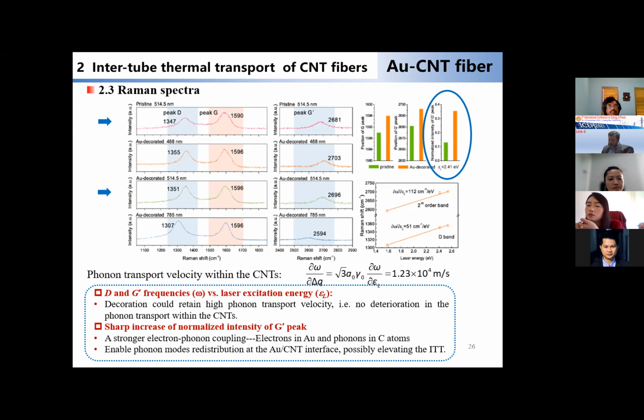Further examination of the frequency against laser excitation energy indicates that gold decoration could retain high phonon transport velocity, the same as the group velocity of the pure tube. That is, a slight decoration of gold nanoparticles will not deteriorate the phonon transport within the tubes.